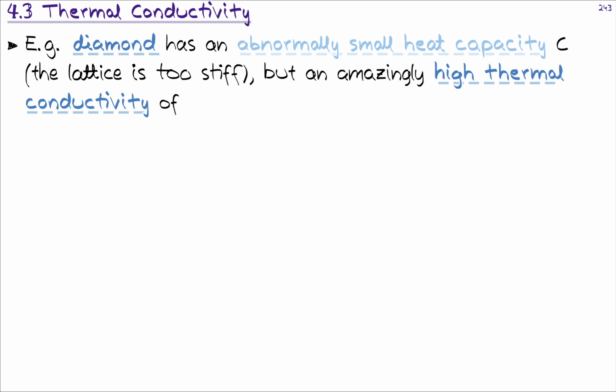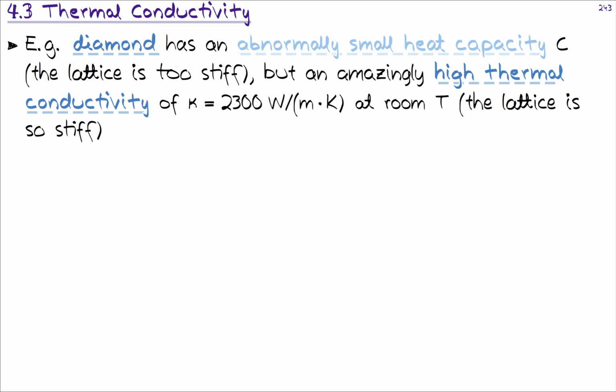And this is, in terms of values, the kappa is around 2300 watts per meter per Kelvin at room temperature. This is among the highest values found in materials, and this is for a normal diamond. This value can be increased even further if you make the diamond isotopically pure. And if you go to lower temperatures, the thermal conductivity of diamond would increase even more.